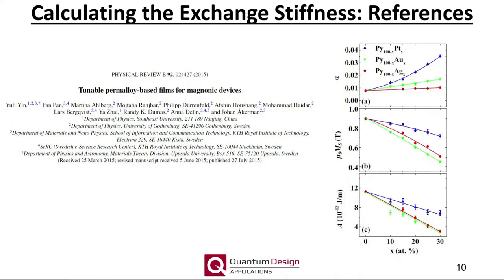Here is an example from the literature where this analysis was performed on permalloy alloy films to extract the damping, effective magnetization, and exchange stiffness as a function of the atomic percent of platinum, silver, or gold within the permalloy. The goal of this research was to find a way to decrease the magnetization of the film without increasing the damping. Interestingly, the addition of silver was found to decrease the magnetization with only a modest increase in damping compared to gold or platinum.